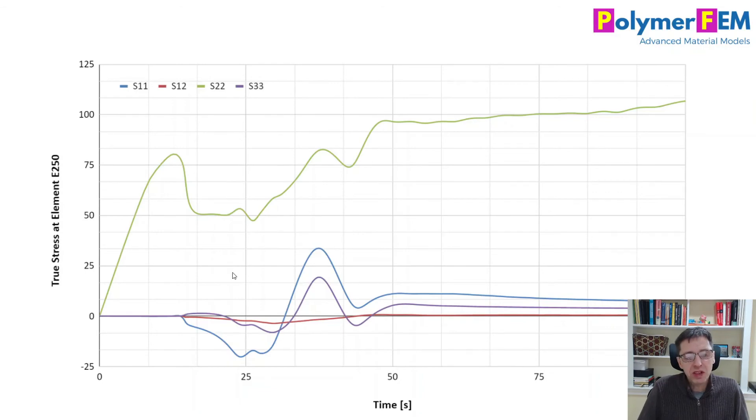So it's suggesting that the reason why we have this interesting shape and kind of odd shape to this main stress is it has to do with also the other stress components which undergo these particular transitions from positive to negative as the element is being sheared and compressed and then relieved from all of that deformation. It's a complicated problem for what's really happening at that element in the center as the neck propagates right through.